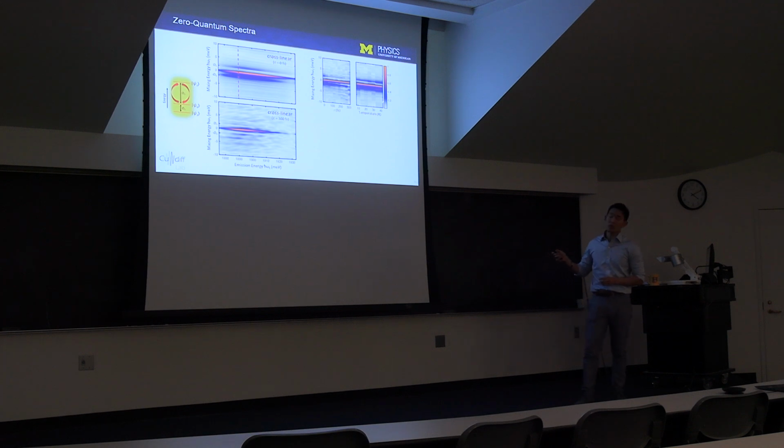From the temperature dependence, we see that the line widths of the sidebands don't change as we increase the temperature to 40 Kelvin. So this indicates that these intertriplet coherences are robust against thermal dephasing. By fitting a slice taken at tau equals 0, we can extract an intertriplet coherence time of 1.36 picoseconds. We perform this fit by fitting the slice to 3 Lorentzians, and we account for the asymmetry in the sidebands by adding an additional phase shift of pi/2 to the sideband Lorentzians. This additional phase shift originates from the different combinations of dipole operators between the sidebands and the central peak.